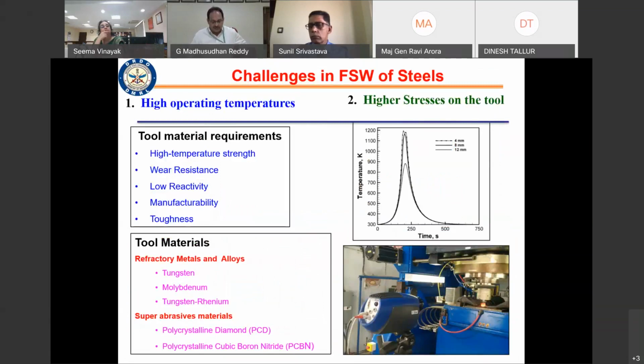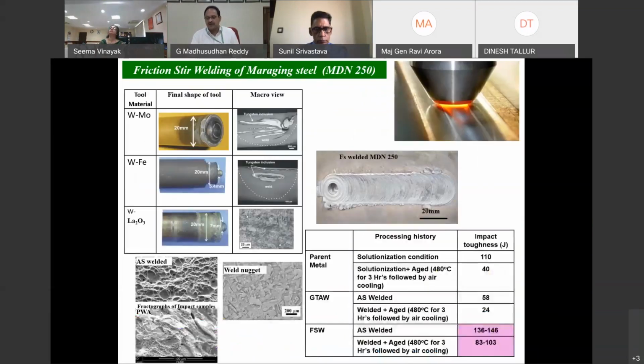The tool should have good mechanical properties, high temperature strength, good wear resistance, and manufacturability. We consider these tool materials, tungsten-based or abrasive materials. During welding, because the operating temperature is quite high, there are quite high stresses on the tool. So we have developed a lot of materials, and we have studied a lot by using tungsten-based alloys. With a tungsten lanthanum-based alloy, we are able to weld maraging steels even for thickness up to 15 to 20 mm, and in the process there is no melting involved, and we are able to get good fracture toughness.